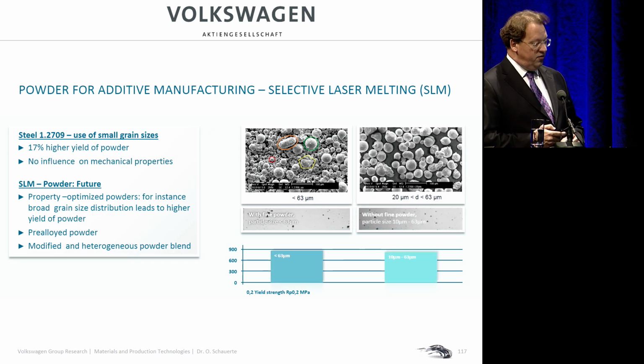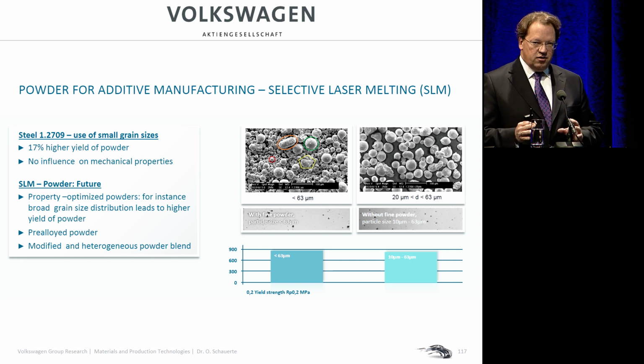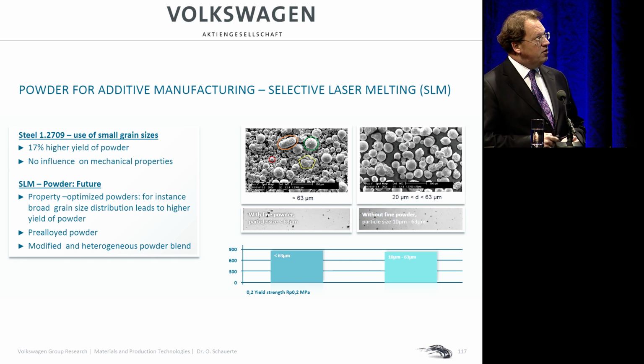Our approach here is, in a first step, that we simply accept, instead of the very, very homogeneous powder, also powder particles with an irregular shape, and also powders that are smaller than 20 micron. Then, by adjusting the parameters in the 3D printer, we have been able to create good material specimens from this powder with a yield strength approximately on the same level as we find with a standard powder.